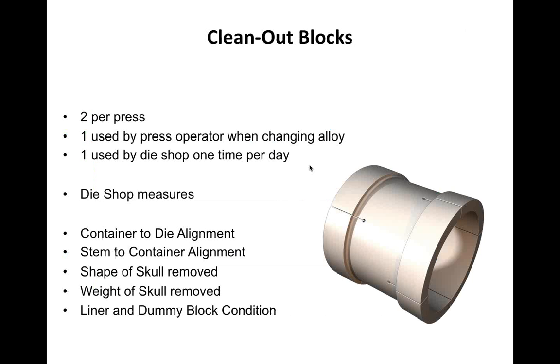Clean-out blocks, number 1, if you don't use a clean-out block, you have a problem. And if you use a clean-out block and nothing comes out of the liner, that no skin is left, you also have a problem. We want the dummy block to leave a skin on the liner somewhere 8 to 12 thou. And if the liner is anywhere from 50 to 100 degrees Fahrenheit less than your billet temperature, between the liner being colder and the difference in expanded diameter between the dummy block and the liner will allow the skin thickness. If you don't have this skin thickness, you're going to be getting surface defects on your profiles and blisters definitely in the back of your billet or profile.